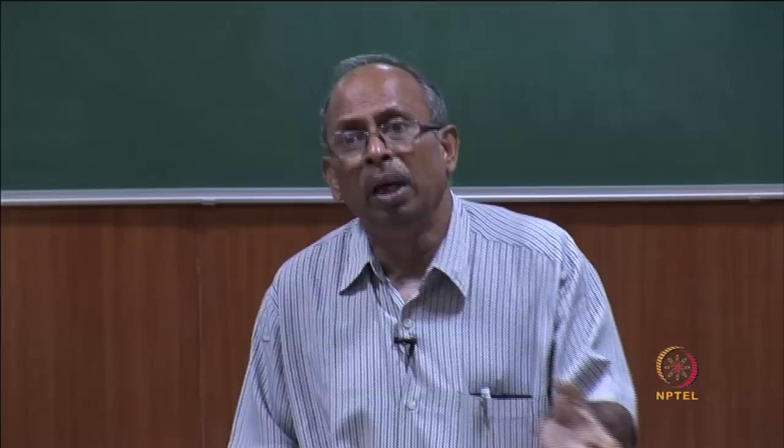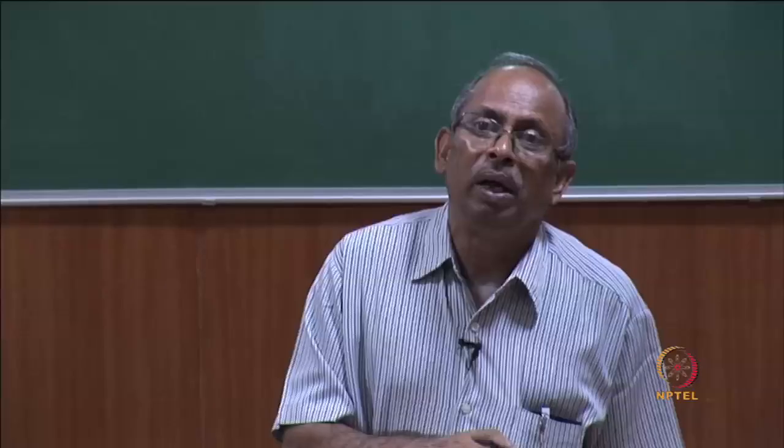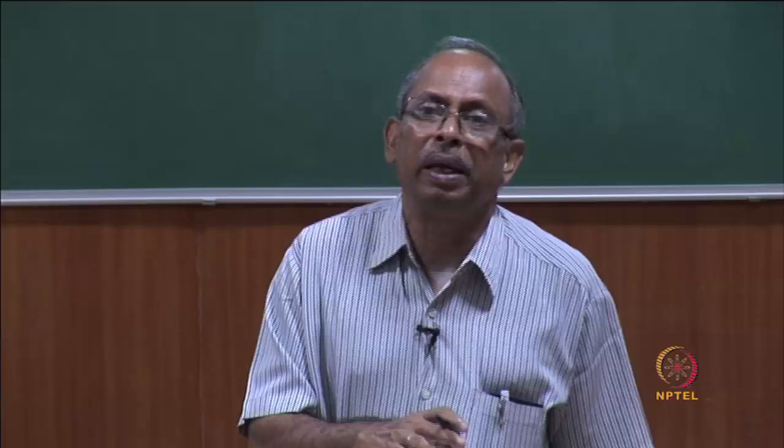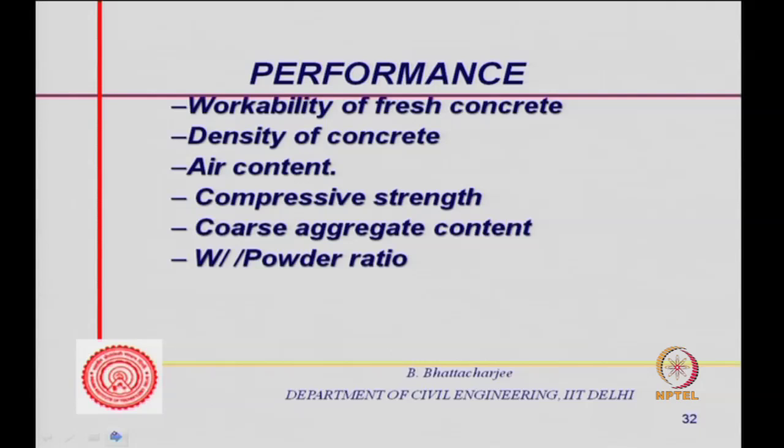So, coarse aggregate content you can measure easily by analysis of fresh concrete, and water to powder ratio you can find out, because whatever is going out, you can again put it on a 75 micron sieve, and whatever is remaining on it is the sand, the rest is water and powder. The analysis of fresh concrete can be done to find out the cement content, water to powder ratio, and powder content.